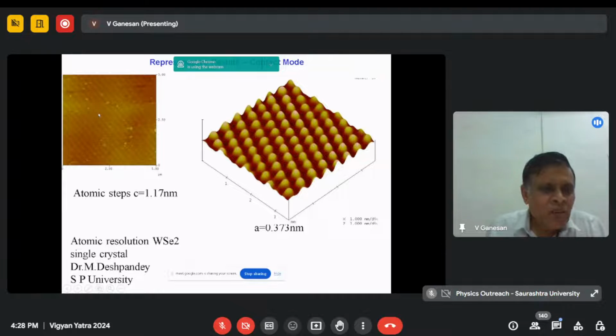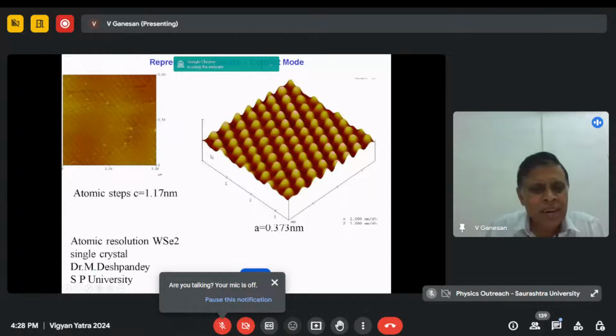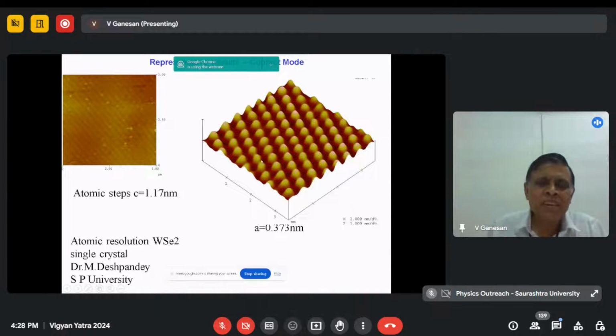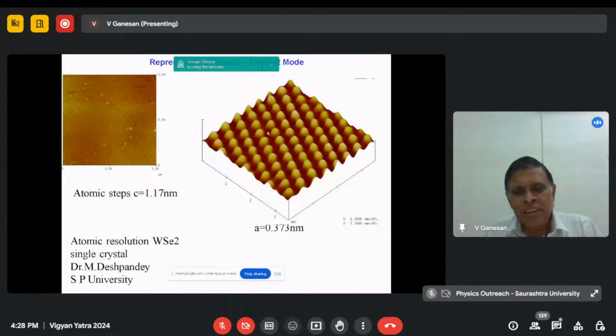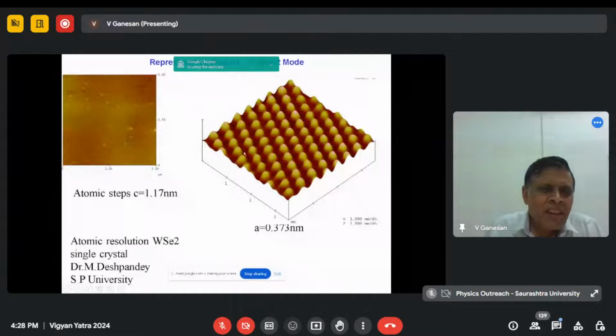Now, go and sit on one of these staircases and then go to much higher resolution. This is in 5 micron, this is in 5 nanometer. So go by 1,000 times precision. You will see a very beautiful hexagonal lattice of the tungsten diselenide. Here the distance between the two atoms is roughly around 3.7 Angstrom. So this I understood. This is the ab axis, and the lattice parameters of them will be 3.7 and 11.7. How did it happen? Very interesting.